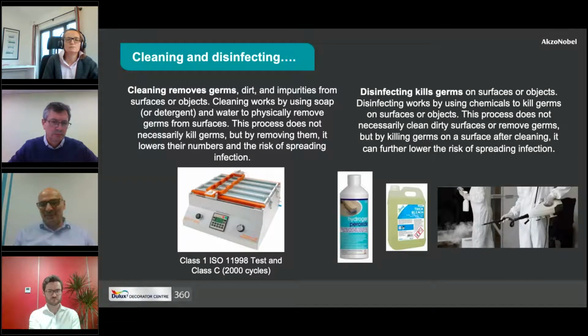We test our products to an internationally recognized standard. It's called the scrub test, and I'll tell you a little bit about what that means. Basically, we take our products, SteriShield or Diamond products, and we do a paint drawdown, and we put a surfactant solution, which is effectively like a diluted washing up liquid, on the surface paint film. We then take a scrub pad, which is similar to a Brillo pad, and we move it across the surface of the paint film a number of times. For our most durable products like SteriShield and Diamond, we do this for up to 2,000, sometimes even 10,000 times.